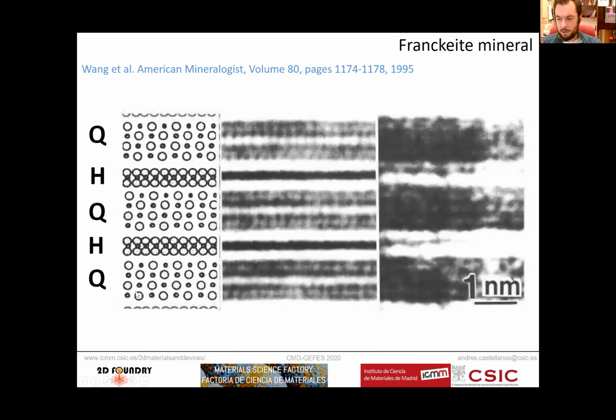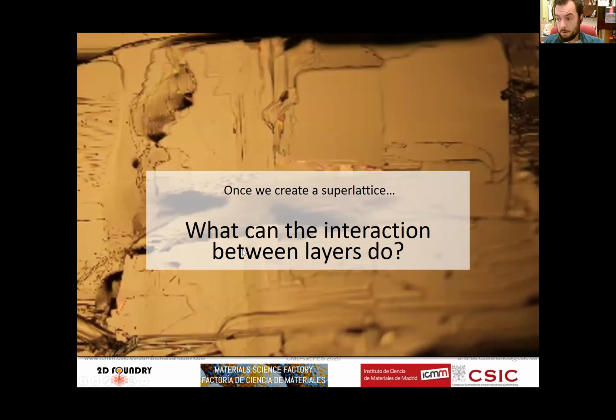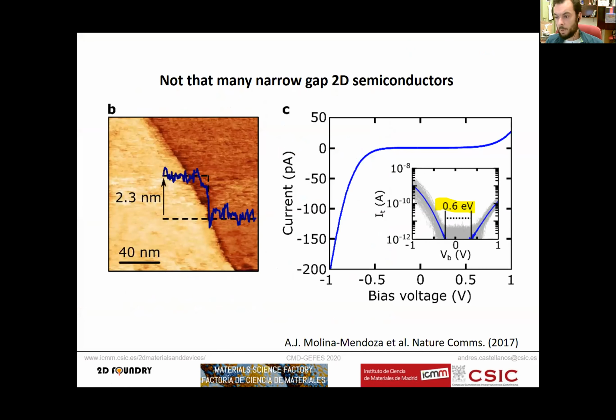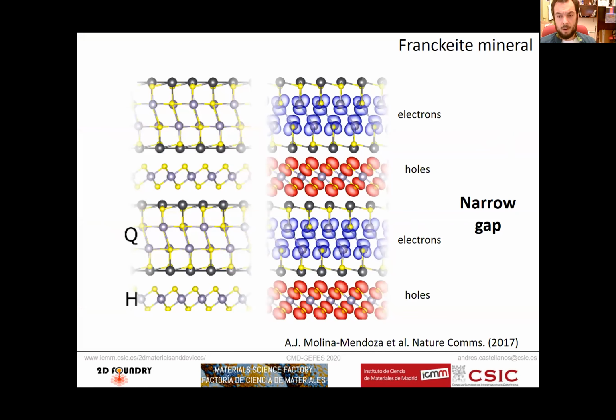Okay, so this layer here resembles galena, so lead sulfide, and this layer here is basically tin disulfide. And then you have these alternating layers of lead sulfide, tin sulfide, lead sulfide, tin sulfide, etc. So this is already quite interesting. And once you have this superlattice, what can the interaction between the layers do to it? Because the idea of a superlattice is that just by assembling this periodic superstructure, the properties of the compound have to be different than just the sum of the individual layers.